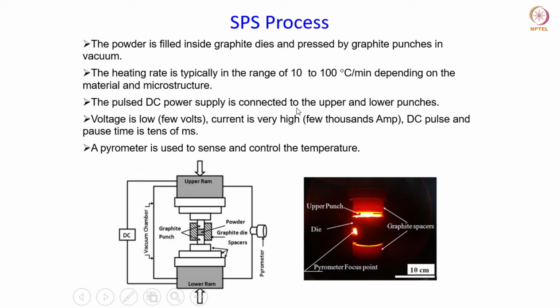Here the current levels are very high, to the tune of a few thousand amperes, but the voltage is low, so it's a low voltage, high current process, and the DC pulse time is of the order of tens of milliseconds. Okay, and a pyrometer is used to measure the temperature.